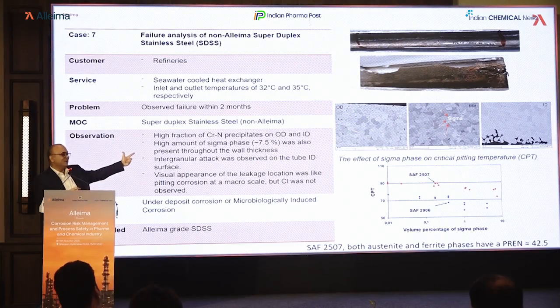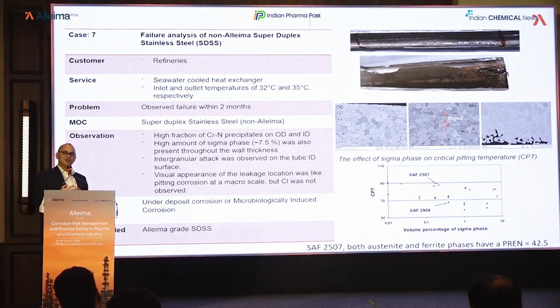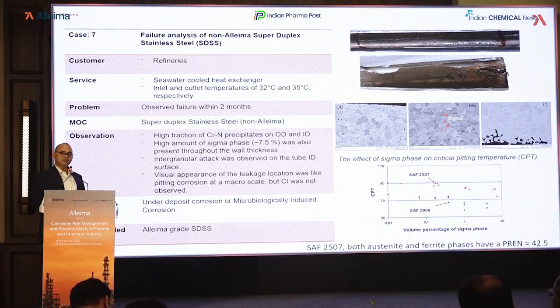Because you had something like the intermetallic phase that we talk about, the sigma phase, and you have nitrides. Whenever you have nitrides like chromium nitride or sigma phase, the CPT, the critical pitting temperature, will come down, and it started failing just at room temperature. So here the grade was right, seeing the temperature, super duplex should work. But due to this problem, basically the heat treatment was the issue, so this didn't work.